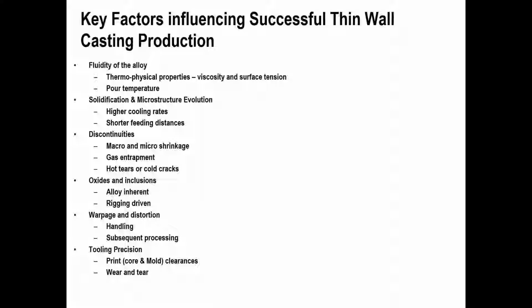So jumping a little bit here, obviously for us on the metal casting, the lightweighting comes by reorganizing the features and, more importantly, thinning the walls. And how do we do that successfully in production? So these are some of the key factors that influence successfully implementing or making thin wall castings. The fluidity of the alloy, which drives how thin you can make, which is driven by the thermophysical properties, namely the viscosity and the surface tension, and the process conditions, the pour temperature, which typically, with most of the alloys, the higher the temperature above the liquidus, you tend to get better fluidity. But there are penalties with that, which I'll also deep dive.